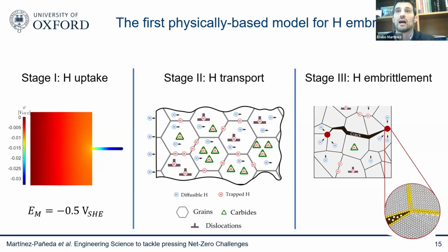And this is also useful for hydrogen production because we're resolving these hydrogen evolution reactions that the people in hydrogen production, so electrolyzers and so on, are interested in. And then once you know how much hydrogen is in your metal, you have a concentration here. You want to figure out what is the distribution of hydrogen within your engineering component as a function of time, and also within the microstructure of your metal, because that's going to tell you whether fractures are going to initiate or not. Hydrogen not only travels freely through the crystal lattice of your metal, it's also what we call trapped,